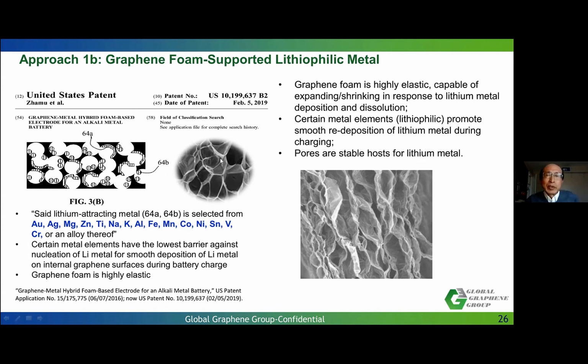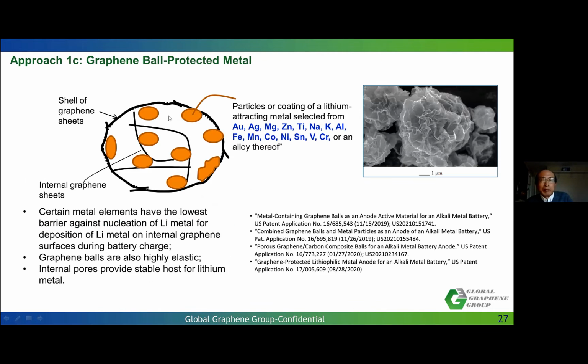Another approach that we have taken by using graphene is to form the so-called graphene ball. Schematically, we have graphene inside here and also outside, and then of course inside you have a high level of porosity. Again, you also introduce those lithophilic metals. And again, this one can address the so-called dendrite initiation and propagation issue here, right?